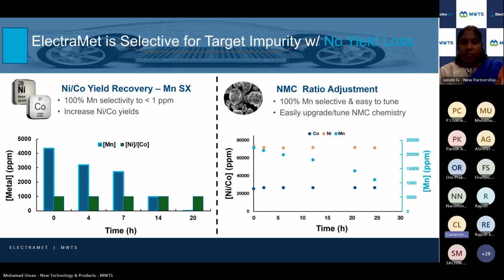And here's some kind of a little extra flavor. If you look at these solvent extractions, right, they do solvent extraction to remove manganese impurity, but that will bring over some nickel and cobalt. So that's typically a yield loss that you're stuck with. And at a big plant, this can be a significant amount of these metals, and it's a lot of lost value. So we had one client ask us, hey, we have this manganese solvent extraction that contains 1,000 ppm of nickel and cobalt. Can you remove the manganese and give us a purified cobalt stream? So that's what we were able to do here. Even though you had a small amount of nickel and cobalt, through our electrochemical process, we're able to get that manganese down to purity specifications. So they now have a second stream of a high purity nickel cobalt process they can then recover instead of having to sludge out and send to a smelter.